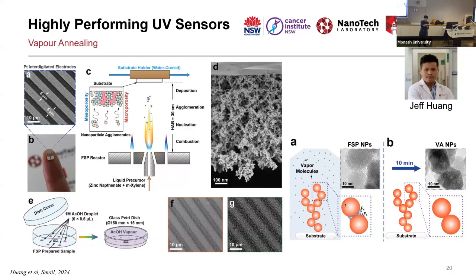For scalability, one of the substrate holders we have is actually moving. We deliberately made it go back and forth because we wanted to coat a large area. But I can imagine the same scenario on a kind of rail, coming and going, and then you change the speed, and based on that, you can change the thickness. In terms of reproducibility, we don't do that, but I'm aware that some people measure the resistance of the film during the deposition. Once it reaches a certain resistance, they cut it, so they can guess that it is the same thickness. We don't do that.